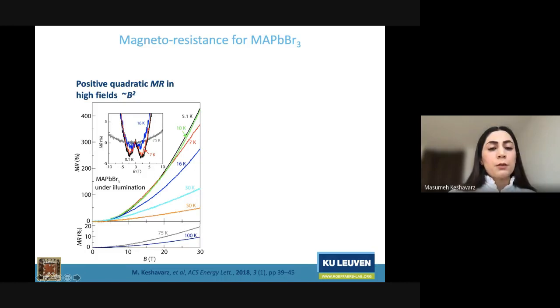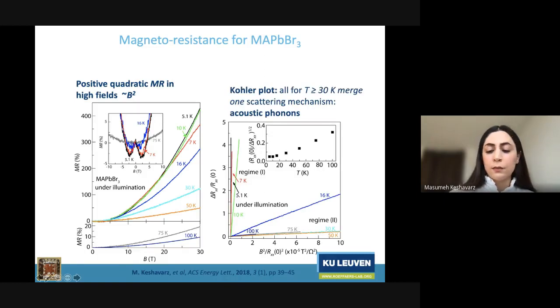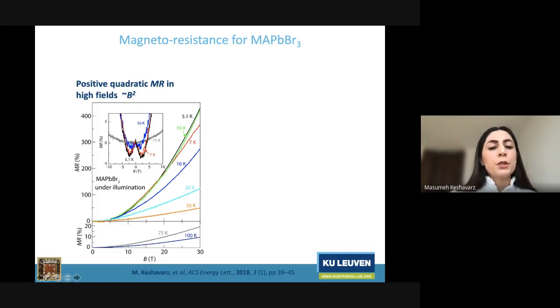However, if we zoom into the lower temperature and lower field data, we see a negative magnetoresistance, which is actually because in this regime, the transport is governed by the hopping of the carriers, and the small magnetic field is increasing the carrier path length, and by moving them, and then when we increase it further, it scatters them. So here there is actually enhanced field-induced carrier transport.